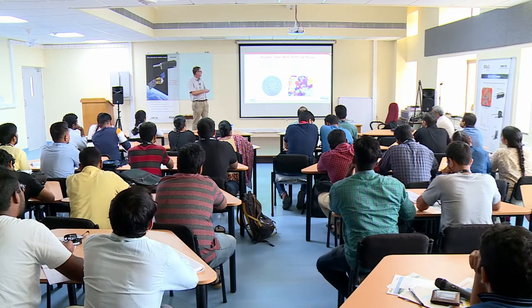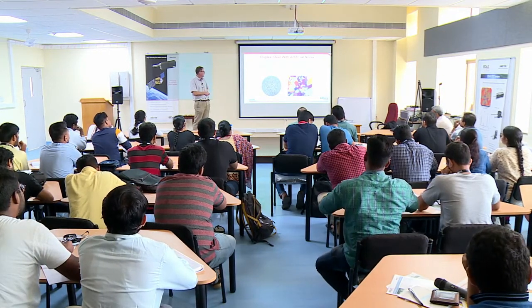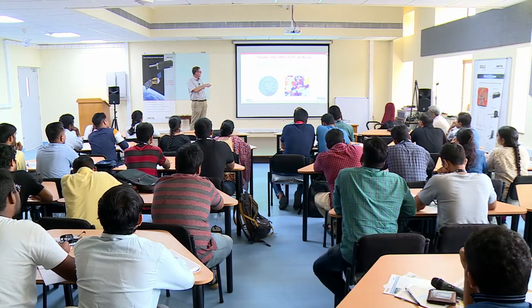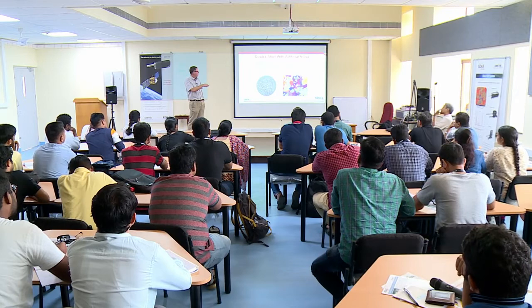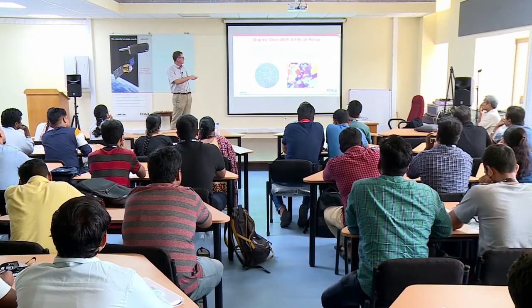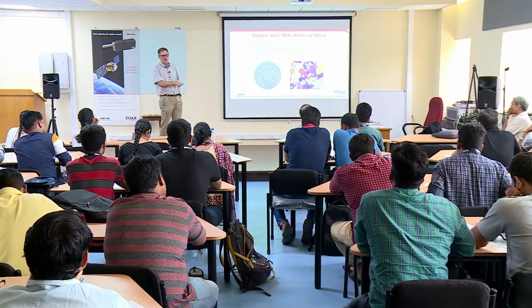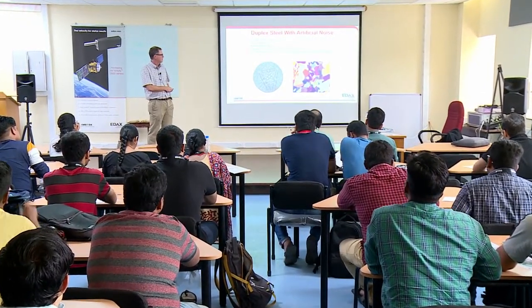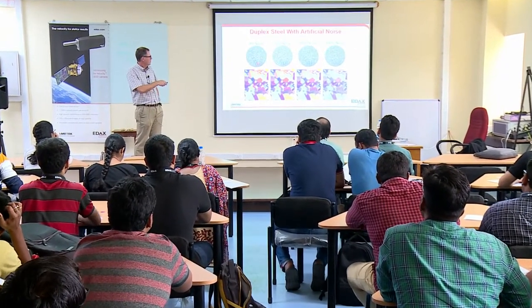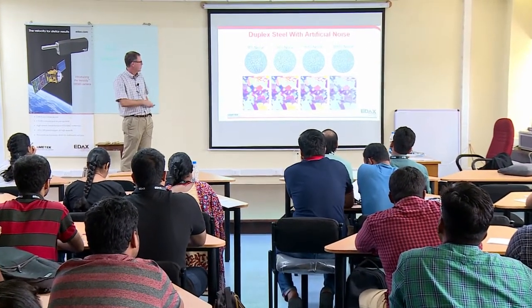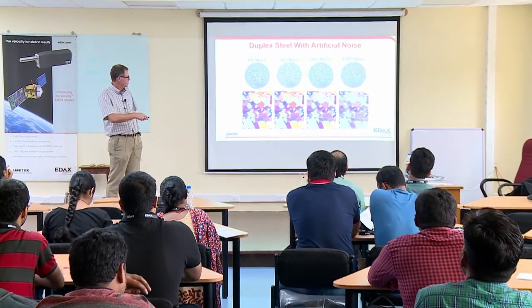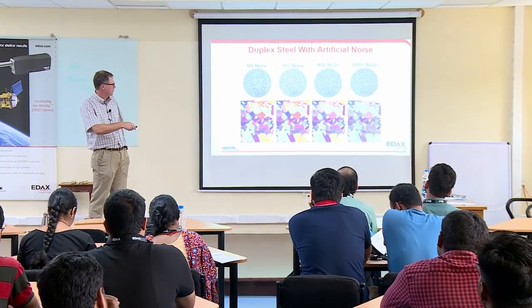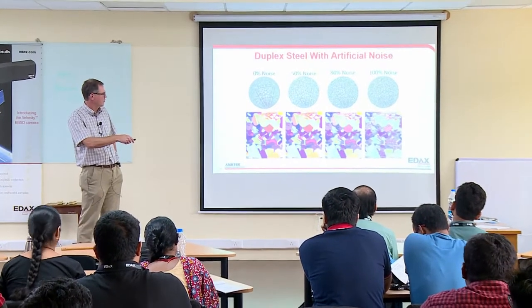So here's an example, 130,000 points on a hexagonal grid. We're using 96 by 96 pixel patterns. And what I'm going to do now, so I can compare, is add Gaussian noise in fractions between 0 and 1 to these patterns. So we can make the reference scan in this case the original scan without any Gaussian noise added. So here's 0% noise, 50, 80, 100. So even with adding noise, we're able to index. I mean, this is pretty good at 50%, but we start to see the effects here and really see it at 100% noise.